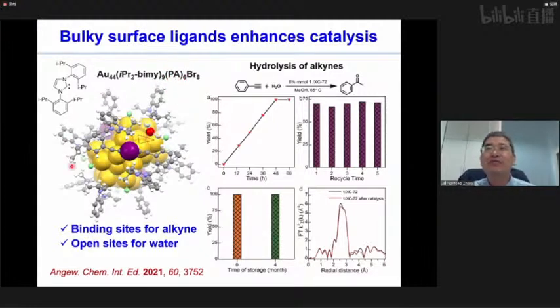On the surface, we can identify that we do have this gold(I) as the binding site of the alkyne. And because this carbene ligand is so bulky, on the surface we have open metal sites for water binding. Which means that by using these clusters, we already have the binding sites for both reactants, alkynes and also water. So it turns out this catalyst is highly active for the hydration of alkynes.